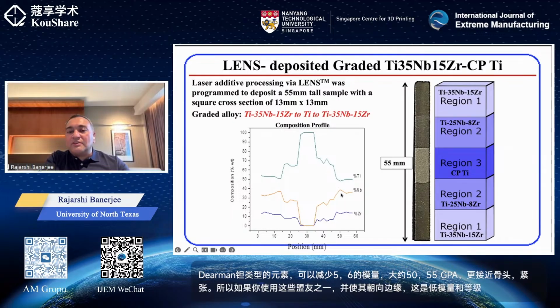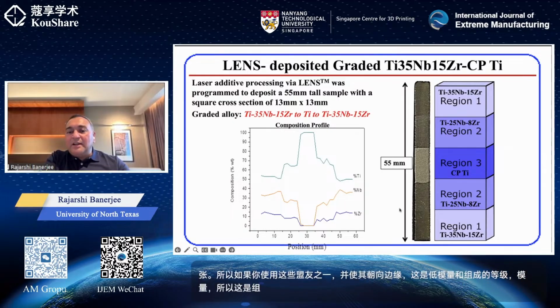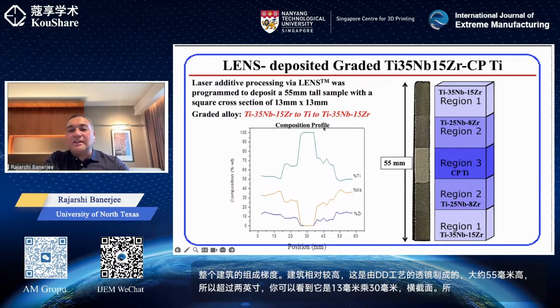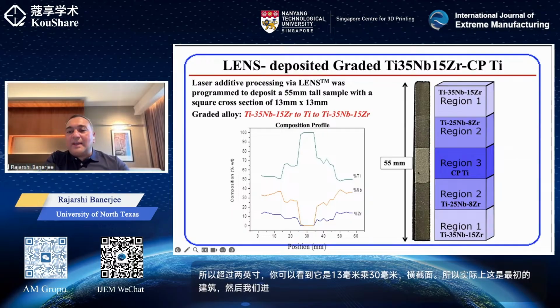So this is the composition gradient across this build. The build is relatively tall. This is made by LENS or DED process, about 55 millimeters tall, so more than 2 inches. And you can see that it is a 13 millimeter by 13 millimeter cross section. So actually this is the initial build, and then we machined it. But you can see the composition steps are given here.